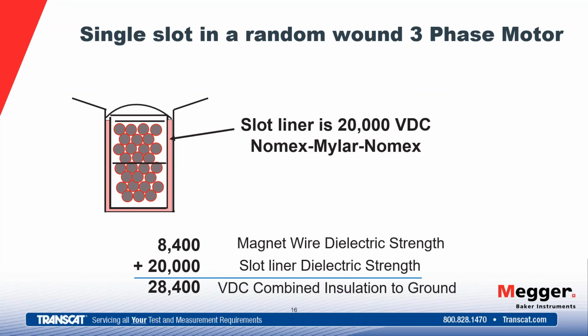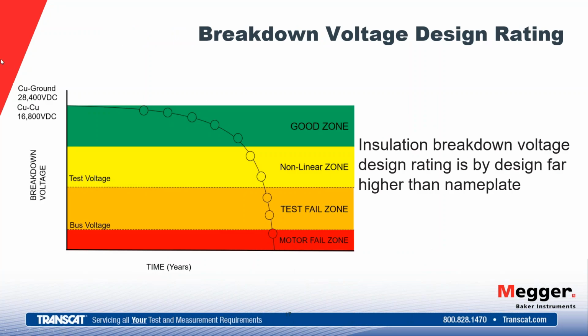So for a 460 volt motor, NEMA would tell us that the magnet wire's dielectric strength, so the insulation around the wire, is going to be at 8400 volts DC. The Nomex itself, and this particular Nomex being used here, is at 20,000 volts DC. We combine those two, the 8400 from the magnet wire insulation and the 20,000 from the ground wall insulation, and we have a combined strength there of 28,400 volts DC to ground. So that's where that motor starts in its life. It was designed to start there.